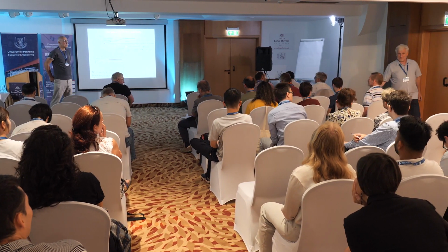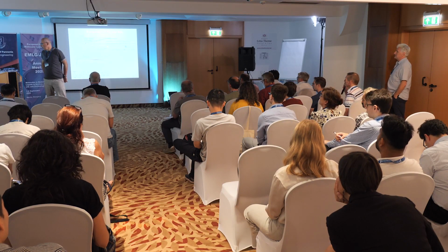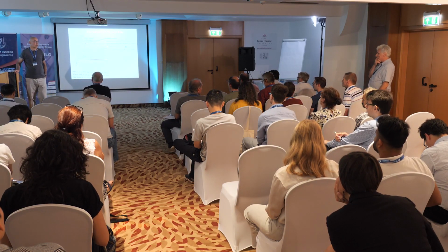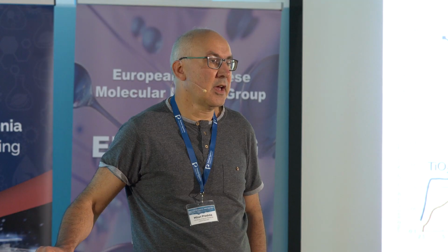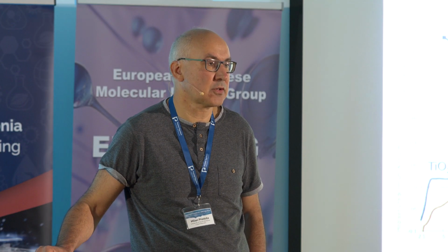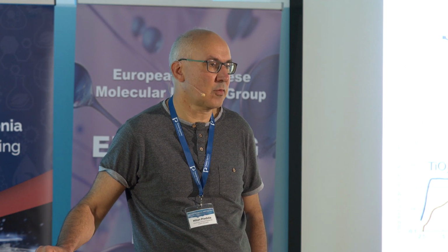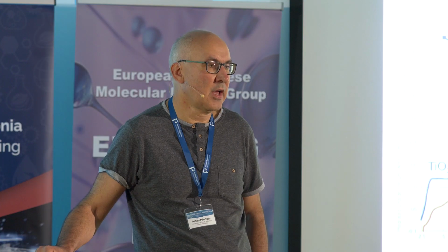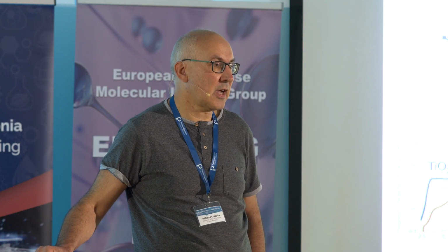Short question: you assume that the surface charge is uniform, yeah? No, definitely not. It's a realistic charging. So, for example, if you want to make the surface charge negative, we adsorb more OH minus groups on the surface. And if you want to make it positively charged, we add hydrogens to some of the surface oxygens. So there are specific atomic charges on each titanium, oxygen, and hydrogen ion, and they even change. It was calculated by ab initio, so it's really atomistic charging.